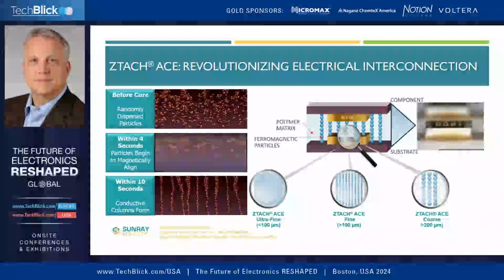So it's obviously an anisotropic material, so it doesn't require patterning. It's designed to handle fine pitch. We have patents on both the particle science here, which is a ferromagnetic particle that's encapsulated either in silver or gold. And then that's dispersed into the base of our thermally cured material, a 2-part polymer epoxy. We also have a UV cured version that's an acrylate-based system. And that material can be deposited basically in the footprint of the component.